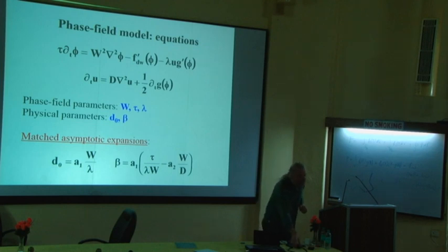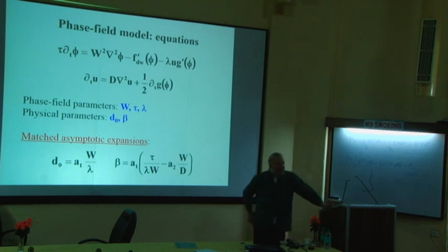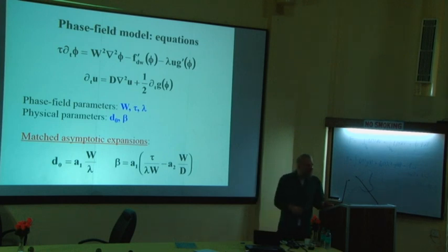This is essential because I have shown you this nice molecular dynamics simulation of a solid-liquid interface. So you have seen that the real interface is diffuse, but its thickness is 2 or 3 atomic layers. Right? If I have a hyperbolic tangent that has as a characteristic thickness this scale, which means 1 nanometer, you have seen in your tutorials your discretization has to be of the same order of magnitude as this interface thickness.